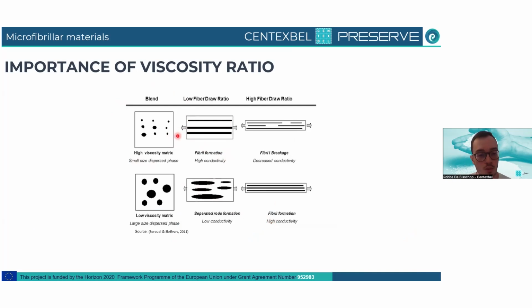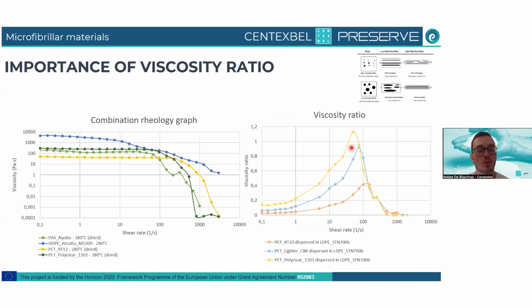and you get nice fibrils after drawing in just a cast film extrusion. If you do the same process in, let's say, filament extrusion, you will maybe already have some fibrils during compounding, and then you also use a very high draw ratio, you can actually break these fibrils up so they have a decreased ability to improve the properties of these materials. So depending on how you process these materials, this will vary.